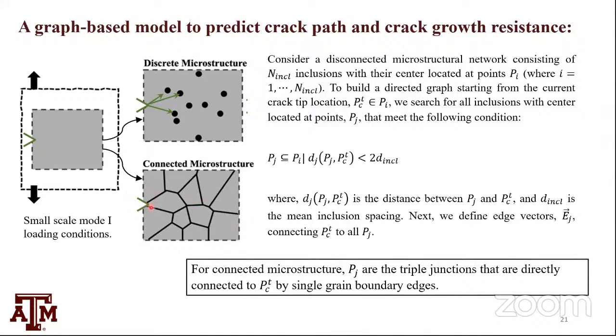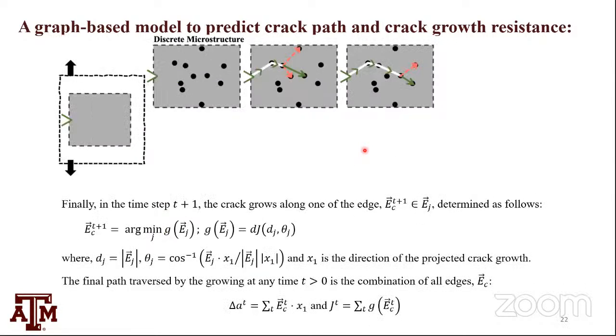In this case, I have only two possibilities. Each of these are triple junctions. So I have only two possibilities, two vectors, easy to define. So I can build my graph part by part. In this case, I'm just focusing on the immediate two edges ahead. In this case, I'm focusing on the inclusions that lie within this two times the mean inclusion spacing. Now, this factor of two is really rooted in the fracture mechanics that we know to date, correlating microstructure and crack growth resistance.